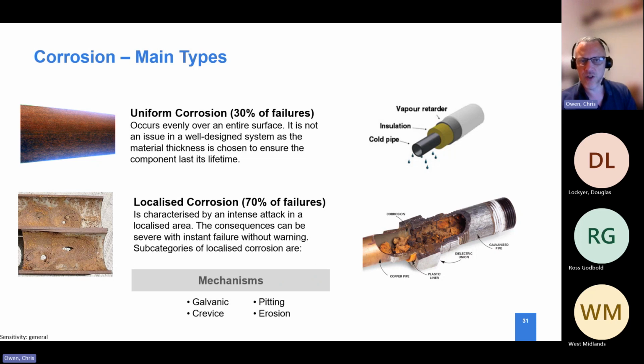Most of the concerns or issues we tend to see now are normally to do with corrosion on the outside of the tube. That's taking place in a uniform manner because any insulation which has been put around the tube has got wet or damp, or there's moisture in there. That means you've got water and oxygen sitting on top of the tube, which can break through any protective coating and cause corrosion.